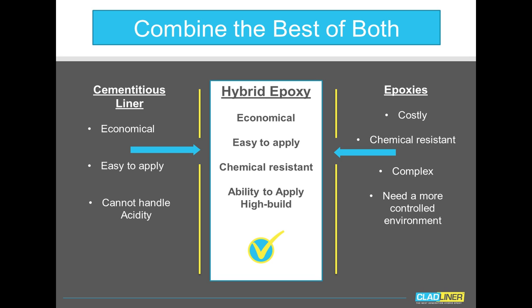So, if we fast forward now, when it comes to epoxy-modified mortars, what we want to do is try and combine the best of both the epoxy and cementitious liners. Okay? When we look at cementitious liners, as we discussed before, the great things about cementitious liners are, as we said, they're economical, they're easily available, they're very easy to apply, very easy to understand, and very forgiving. But they're not so great with acidity, which we find in this environment.